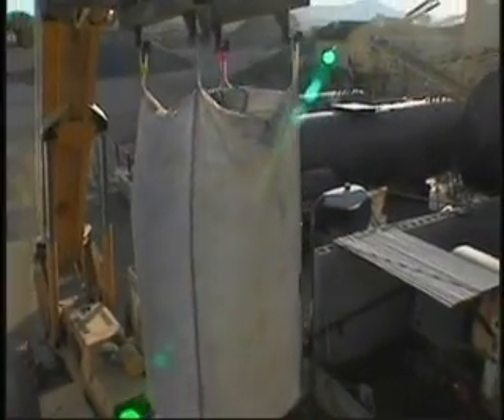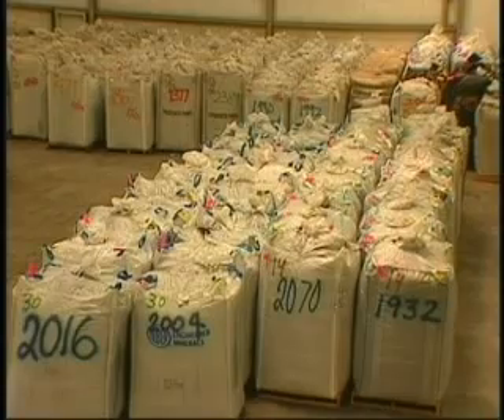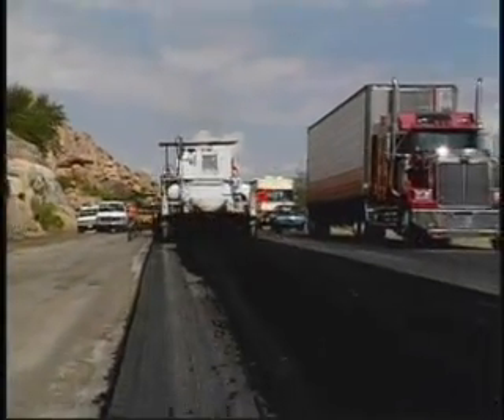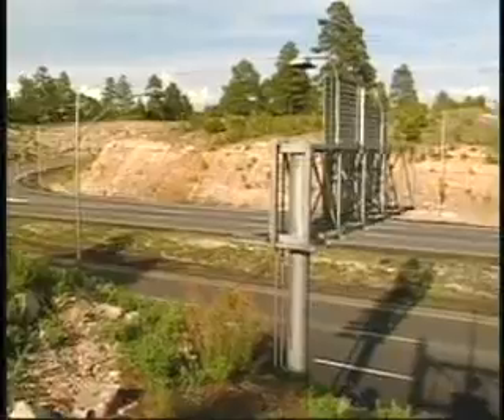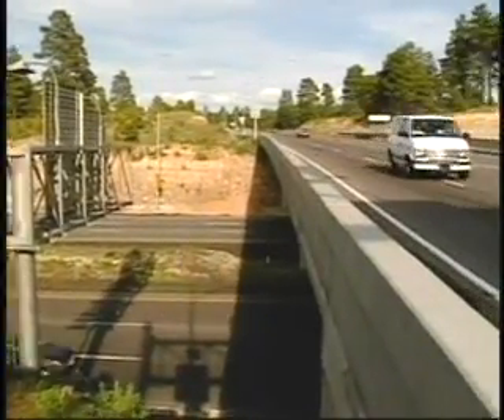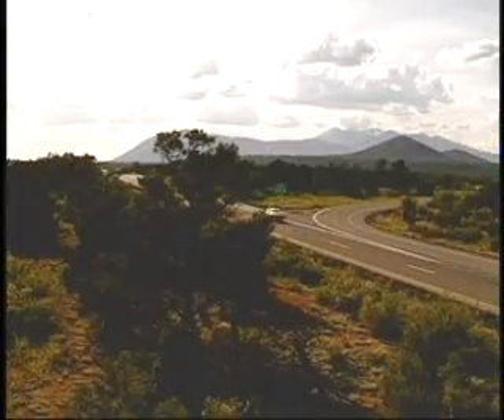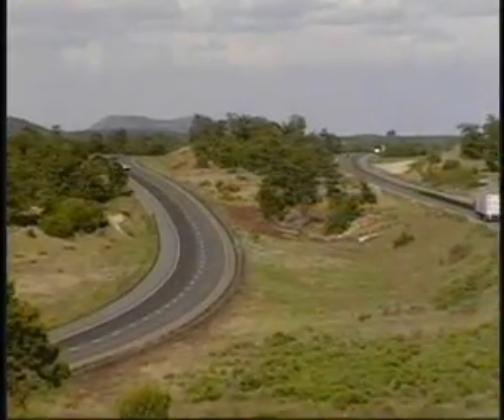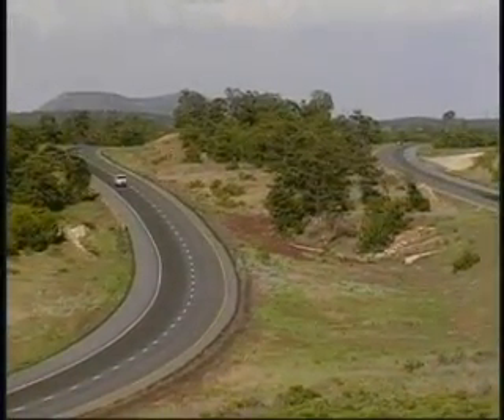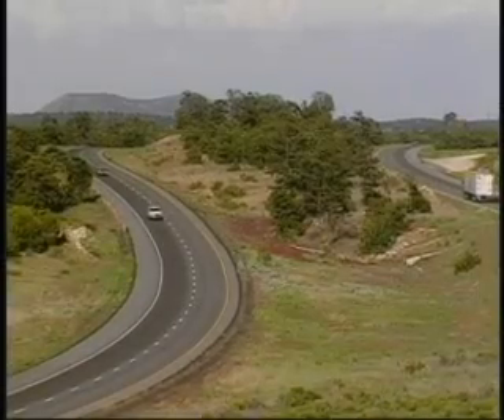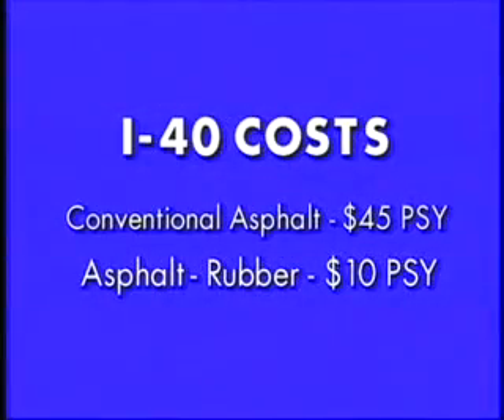Initially, it can cost more per ton than conventional asphalt, but it's the total project cost that tells the story. On a section of Arizona's Interstate 40 near Flagstaff, at an elevation of about 7,000 feet, a 5-mile section was reconstructed in a conventional manner for a total cost of about $45 per square yard, and it took 2 years to complete. Later, an adjacent 10-mile section of the interstate was overlaid with asphalt rubber in just 4 months for a total of only $10 per square yard.